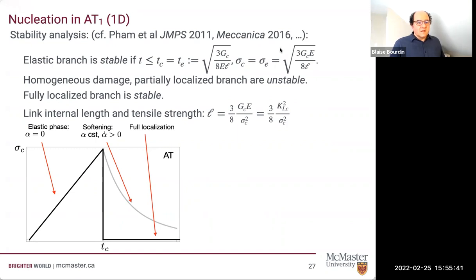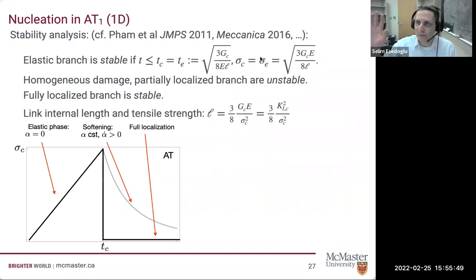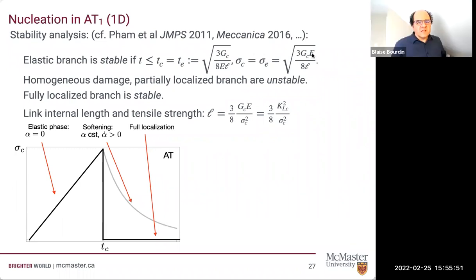And the load at which your crack nucleates, or the stress, is given by this relation. GC is the toughness, E is the Young's modulus, L is the regularization parameter. If you know sigma C, GC, and E, you can compute an L such that the stress at which you will numerically nucleate a crack is equal to sigma C. So it's given by that.